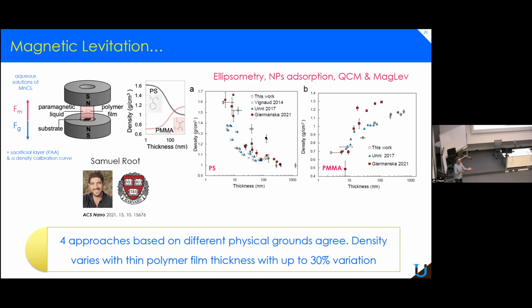Well, actually, there is a substrate at the beginning because they have to make the film. They spin coat a layer of polystyrene on top of a small layer of PAA, polyacrylic acid, deposited on the wafer, and you put it inside the machine with the paramagnetic liquid, and so the film will float off quickly, and afterwards the film will basically float around in the fluid, and the height will correspond to the density that they are able to calibrate with beads of known density.